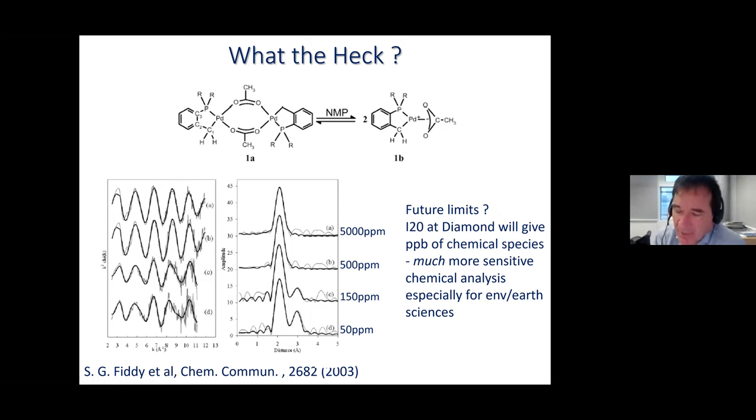was that as you diluted it further, there was direct evidence that the dimer dissociates and produces a measurable amount of the monomeric species. Now, this measurement here, this is 50 parts per million. This was done on a 20-year-old spectrometer. With modern, brighter, higher resolution spectrometers, you can perform these measurements at least 1,000 times brighter. Sorry, to a thousand times lower levels. So modern XAFS techniques allow us to provide chemically specific information at parts per billion, for example, in this case,